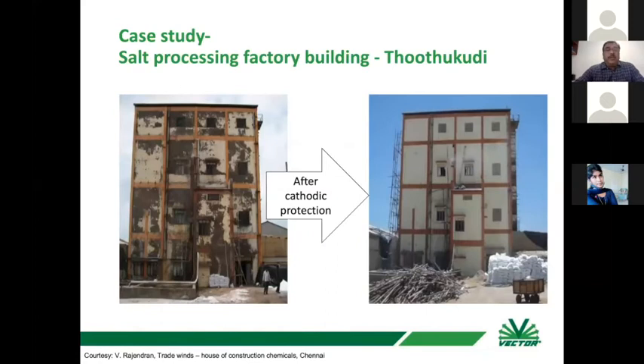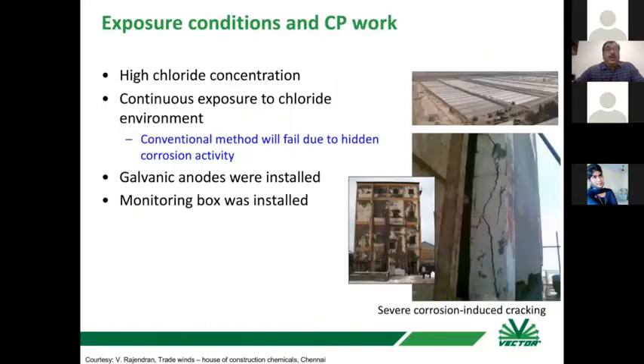Another structure is in Tuticorin, wherein this is a salt processing factory, and in case of salt processing factory, you have a lot of chlorides and various problems. And it was repaired using CP system. These are the before and after photographs. Definitely, there was very high chloride concentration, continuous exposure to chlorides. And with conventional methods, there is already chloride inside and high corrosion activity. So it will fail because of patch acceleration or halo effect, and you can see the various cracks.